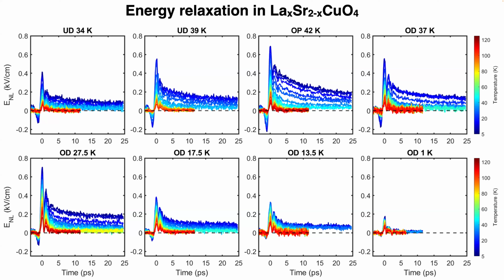It's kind of analogous to what some other pump probe style experiments that have been done over the years, but with lasers. The problem with those experiments is they use very high energy excitations, 1.5 eV. It's a huge energy scale as far as the physics of the cuprates is concerned and the physics of the low temperature transport. So here we take this Fermi surface and we excite it only with very low energy photons, right? A few meV. And we can excite the system using polarized light and look at the rate that energy leaves the electronic system.